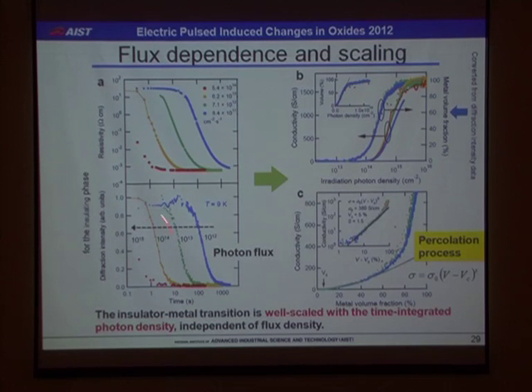So actually, the dynamics depends on the incident flux density. Here, resistivity and diffraction intensity for the insulating phase are plotted as a function of irradiation time. By increasing photon flux density, the time scale becomes shorter and shorter, as you can see. Actually, this behavior can be scaled by the time-integrated photon density. So this means both the conductivity and the metallic volume fraction are determined by the total dose of X-ray photons. And that's a special difference between the conductivity and metallic volume fraction, indicating percolation behavior. And when we plot the conductivity and volume fraction, this is fitted by the conventional three-dimensional percolation model.